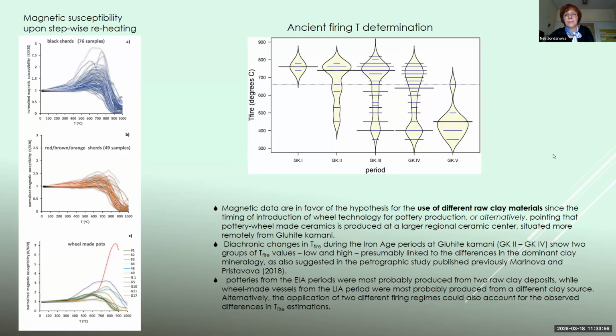And ancient firing estimates show an interesting distribution with regular evolvement of values from high temperatures at the final Chalcolithic. And during the early Iron Age, we have always two groups of samples, one with higher firing temperature and the other with lower, while in the wheel-made pots, we obtained almost only low firing temperatures. And we interpret that as the use of two different clay source materials during the early Iron Age periods, and a different clay source for the introduction of wheel-made pottery.